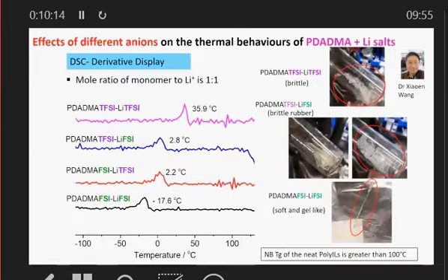Okay, so the initial work then that Dr. Xiaoen Wang, who was a postdoc in my group, and now he's a professor in Dalian with the Chinese Academy of Sciences, investigated what happens when we look at the DADMA TFSI or FSI, and we dissolve a lot of salt. Now, what I'll say is what we're looking at here is not the low concentration of adding salt to a polymer like we do in PEO. We're looking at what we call the polymer in salt complexes. So it's like a solvent in salt where the dominant component is the salt, and the polymer is acting sort of as a secondary component, but a very important secondary component.